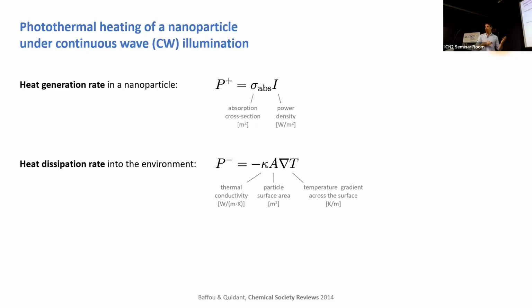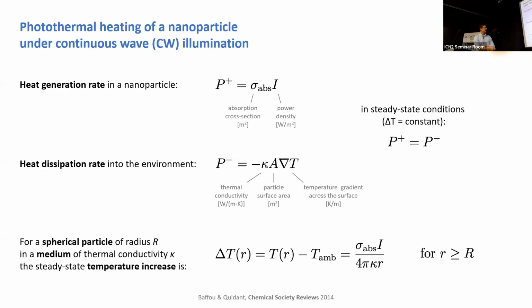Now, we want to find a solution for a steady state condition. So given a certain irradiation intensity, what is the delta T of the particle? So how hot can we make it with respect to the environment far away from it? And so essentially, we need to equate these two, heat generation rate and heat dissipation rate. And if we equate the two, and you do a little bit of mathematics and an integration using the right boundary conditions, in fact, from a physical mathematical perspective, it is the same problem as the electrostatic potential of a charged sphere. So something that we all did in electromagnetics, I think.